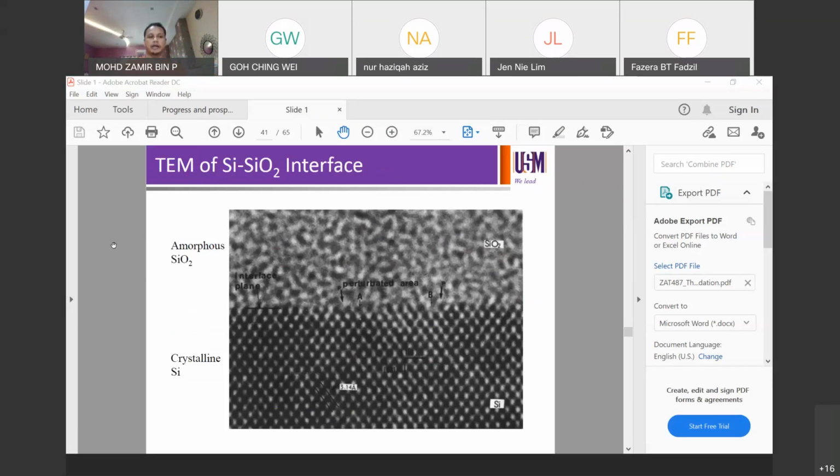crystal orientation, you send a cross section. So you have the SiO2 on silicon, you thin it down, you send the thin sample on TEM. So we've covered TEM last time on wafer characterization. It's transmission electron microscope. So you want to see the interface. So this is how it's gonna look like. So you're gonna have your amorphous silicon dioxide, typically amorphous, on monocrystalline wafer.